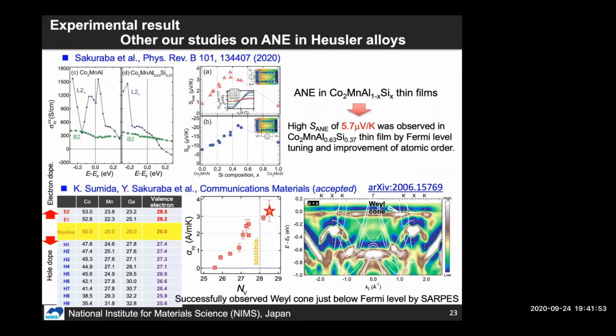But does that match with your transport carrier concentration? Is there anything that can be said from the transport measurements? You can get the carrier concentration where you fix the Fermi level in your DFT, and compare with measuring the film, because from ARPES sometimes you also have these surface states. Though it's a metal, so there should not be much difference between the surface Fermi level and the bulk. But if you can get something from transport, I think it'd be more believable.